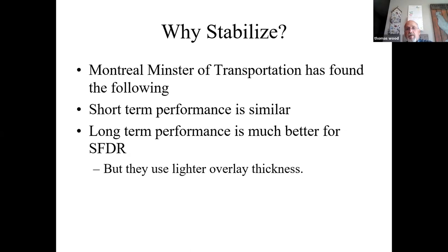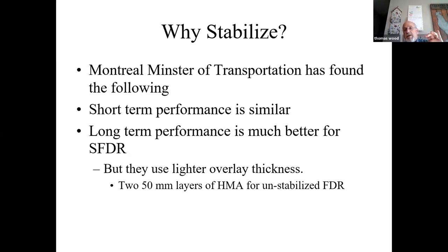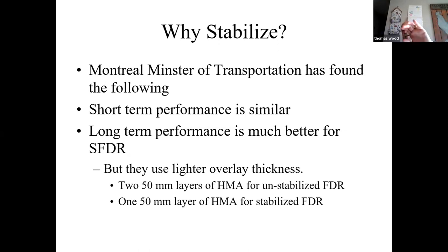unstabilized. But they use a lighter thickness overlay on the stabilized. So on unstabilized, they put two 50 millimeter lifts of HMA on. On the stabilized, they put one. So even if at 20 years they were getting the same performance between stabilized and unstabilized, they're using half the HMA. So there's quite a cost saving.